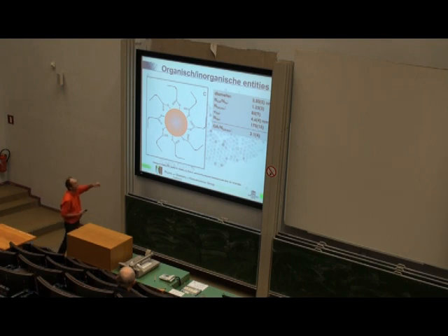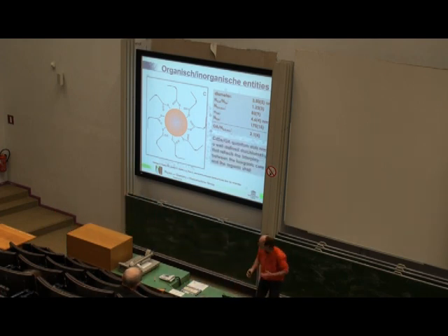And then you can do the stoichiometry, and you see that for every cadmium in excess, you have two ligands, which is not illogical because a cadmium will be 2 plus, and such a single oleate will be 1 minus. So the whole thing actually adds up to make a nanocrystal that is completely neutral as a whole. And there's no charge on this nanocrystal. And so what you see is actually that these nanocrystals are a kind of organic-inorganic hybrid particles, where the properties of the core, the excess of cations, actually will determine how many organic ligands you have around. There's no coincidence there. They have a very well-defined stoichiometry, because the overall particle has to be neutral.